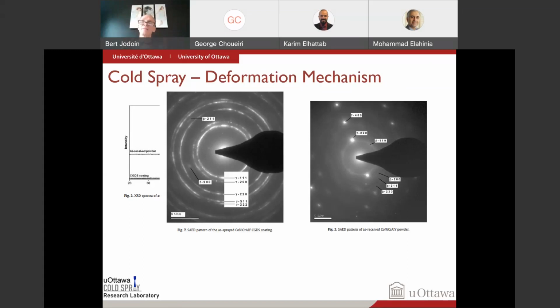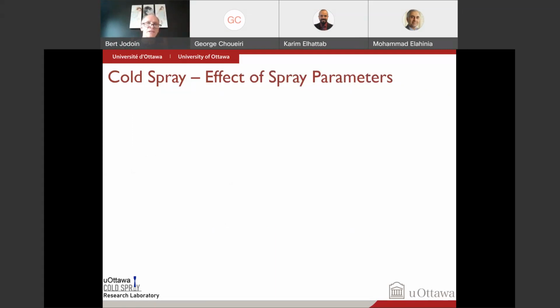So I was lying a little bit at the beginning when I was saying that you don't get any chemical structure change. You do, but at a very, very tiny layer, a few nanometers thick, where you're going to get this nanocrystallization. So again, by studying this, we can better understand what's going on in this complex deformation mechanism.